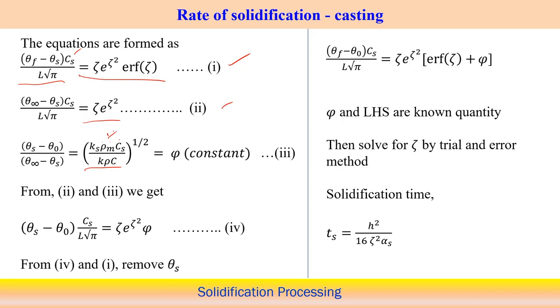Once we reach these three equations, we can explore them further to estimate the solidification time. From equations 2 and 3, we get theta s minus theta 0 into C s by L root pi equal to zeta into e to the power zeta square into phi. This is equation 4. From equations 1 and 4, we can try to remove theta s, because theta s is there in 1 and also in 4.